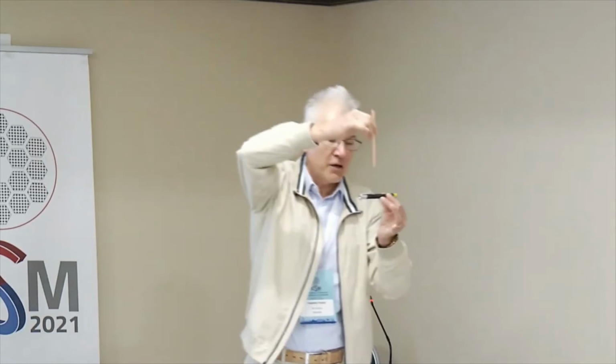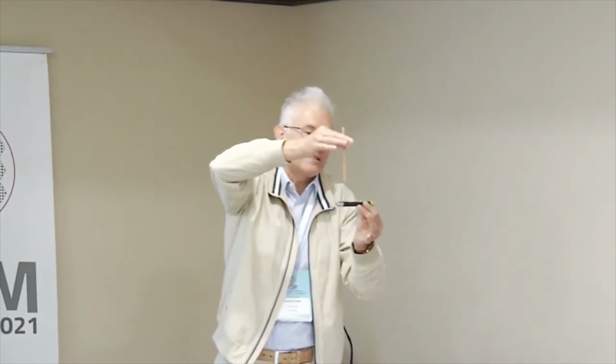For vortices, we need a normal to the surface component of the magnetic field. And here on the top, it's just maximal value. It's the same value as the applied field. In the bottom part, it's the same maximal by modulus value equal to the applied field. But if you go now to the side of this cube, the magnetic field is tangential. Tangential field is maximal, but we do not need tangential field. Vortices do not feel tangential field. They need normal field, and we do not have normal field. And this is just what is shown in the first panel.